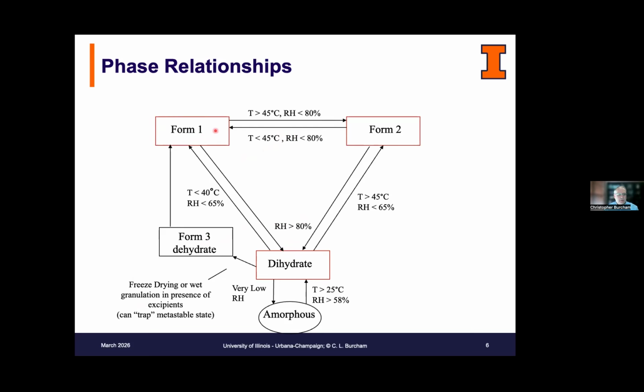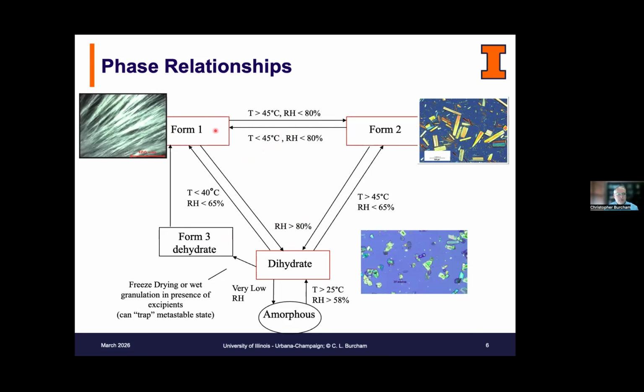And if that were the end of the story, there wouldn't be much of an example here. But in the particular case of Form 1, it crystallized in extremely long needles. It was very difficult to even filter and get out of a reactor, let alone try to formulate. And so it was discovered very early on that Form 1, while thermodynamically the most stable form, was from a process perspective unprocessable, especially at the high drug loadings that were needed for this particular project.